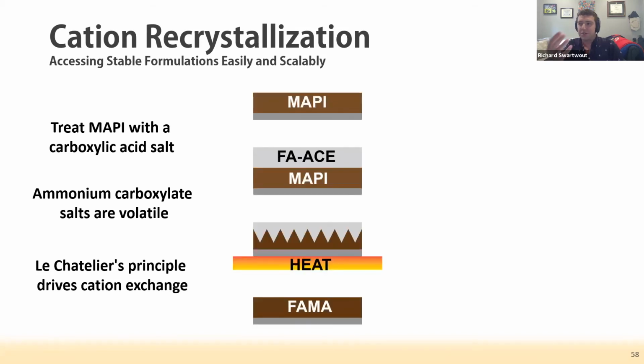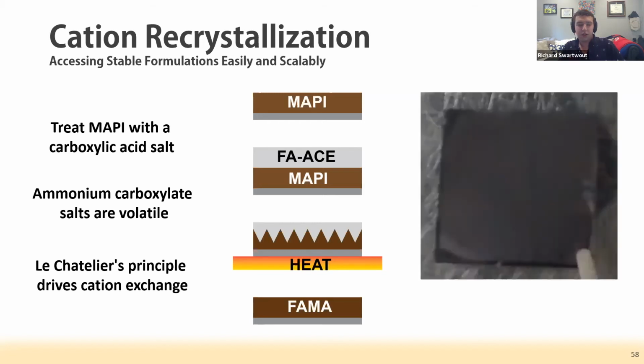Schematically, this is shown here. We just take the MAPI film, treat it with formamidinium acetate, heat it, and that creates our formamidinium-rich film of interest. Here's a video of this process happening. This is just a 1-inch film being placed on a hot plate.